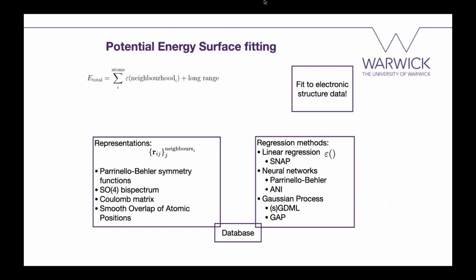In a bit more detail, what we are trying to achieve here is a potential energy surface fitting, where we describe our total energy as the sum of atomic contributions, which are restricted in space, and some long range, which I'm going to forget about for now and just focus on these local contributions. To put it in a more formal way, I show this sum as a sum of atomic energies, which depend on our neighbors within a cutoff. That will be my model, and the physical motivation is the short-sightedness of quantum mechanics.